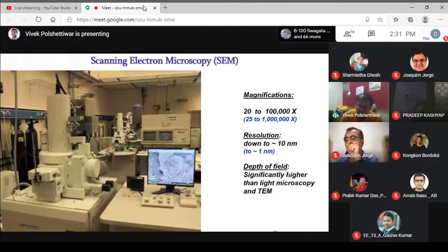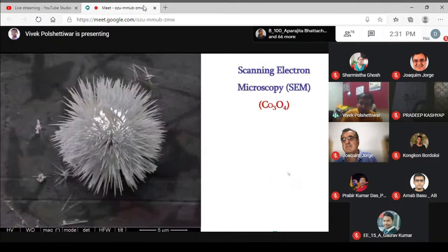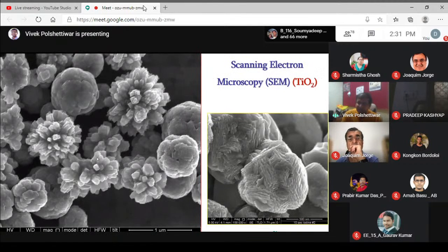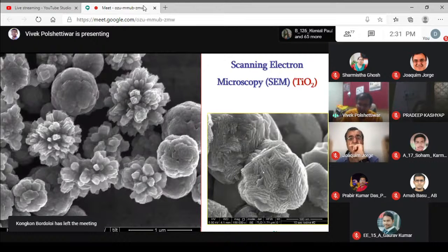This is a scanning electron microscope, and it gives you more surface information, more morphological information. So something like this. This is a cobalt oxide. This is TiO2. You can get a very nice surface morphology. This looks like stacked sheets forming those spheres, or stacked cubes forming those spheres.